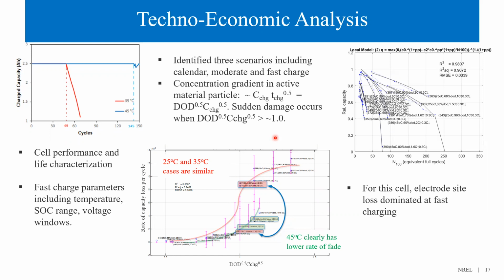Using this statistical framework, degradation mechanisms, along with temperature and the cycling factor, are regressed to produce a lifetime prognostic model. By analyzing aging data from AllCell, three scenarios were identified, including calendar fade, moderate normal cycling, and fast charging cycling. The criteria to distinguish moderate cycling and fast charge cycling is not only related to charging rate,